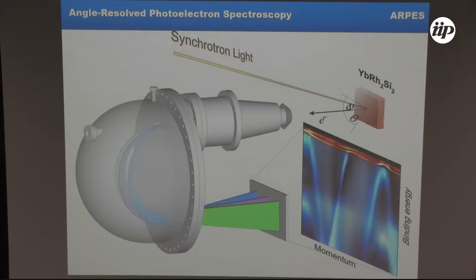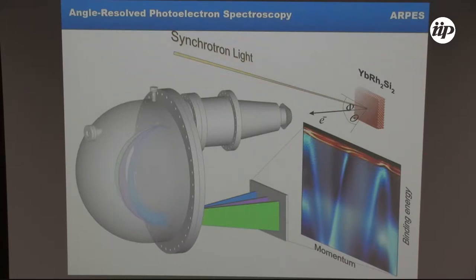Using a rather sophisticated lens system on this machine, you are able to analyze the angular distribution and recalculate — using conservation of energy and momentum — the binding energy and momentum. This basically gives you information about the electronic structure of your material. We look precisely at the Fermi energy region to analyze the highest kinetic energy electrons, which are essentially the interesting ones for these systems.